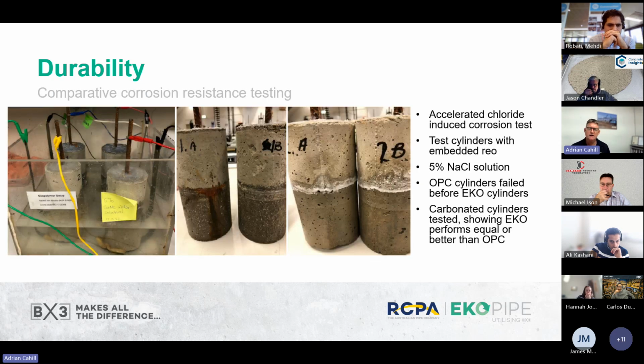One other thing that we've done is looked at testing around corrosion resistance. This was done because of the concerns that are regularly raised with high SCM concretes around the ability to withstand carbonation-related corrosion. So there's a test that was developed in collaboration with the University of Melbourne, where a cylinder is cast with an embedded reinforcement bar. You can see there that the bar is placed down the center of the cylinder.